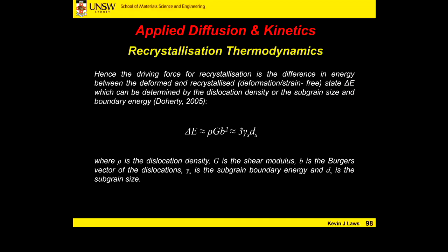All right. So, a little bit on thermodynamics, or trying to apply thermodynamics to this process. The driving force for recrystallization, here we just take it as a difference in the energy between the deformed and the recrystallized, or strain-free state. A delta E, change in energy, which can be determined by the dislocation density or the subgrain size and boundary energy.